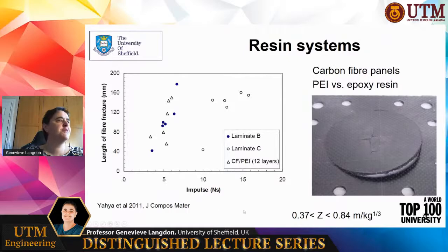So here are some other images from Yahya's PhD, where we looked at how much fracture you get. He looked at the length of the fracture in the fiber, against the increasing size of the blast on the horizontal axis for some different laminates. It's quite difficult here to see any influence of the resin system itself. We looked at panels that had PEI, like on the previous image, versus epoxy resin, and you can't really see much from that.